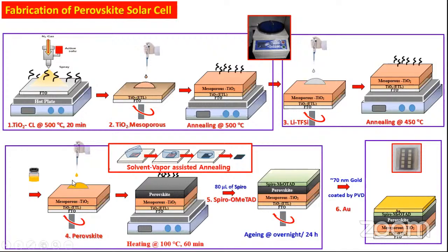Next, the main important light absorber was coated, and after spin coating the perovskite, we need to anneal it on a hot plate. When heating the perovskite film, we need to cover it with a watch glass immediately. It slows down the evaporation of the solvent. With slow evaporation, Ostwald ripening occurs, resulting in larger perovskite crystals. The larger grains form in two ways: one is slow evaporation, and the second is moisture accumulation in the small grain boundaries. Both of these can merge the small grains, so you get larger grains.